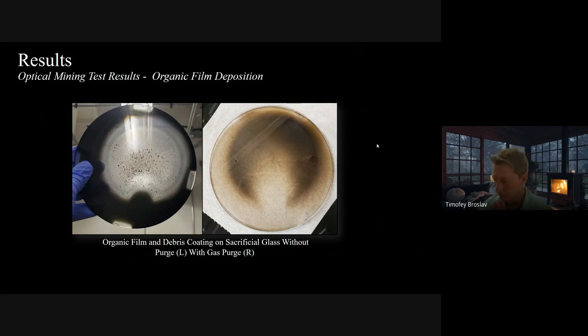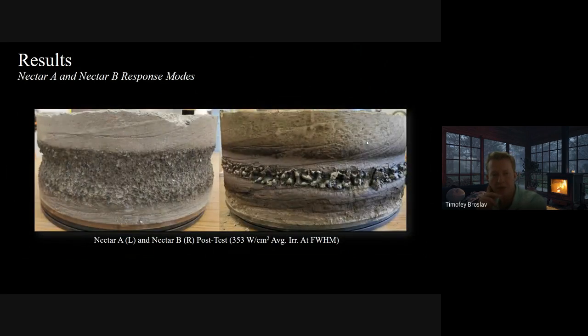It also, I would say, added extra water, because this wasn't 100% pure CO2. It did have some leftover water, or either that or the line was leaky, but it added water into the test system, which basically led to incorrect results for some of the early tests for water production rates.